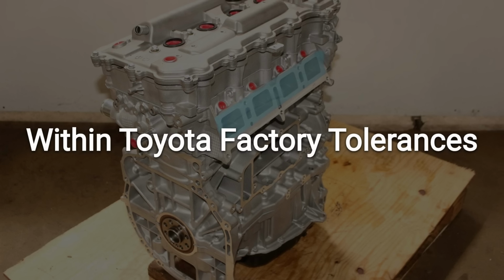The timing chain guides, which are plastic composite pieces that the chain rides against to control chain slap and vibration, showed slightly more surface wear on Car A as well. Neither engine was anywhere close to a failure point. Toyota's timing chains on this engine are rated to outlast the engine itself in most cases. But if you're looking for where full synthetic oil earned its keep, the timing chain assembly is a legitimate answer, because that thinner, more thermally stable synthetic film handles the high-load, high-friction contact between chain and sprocket a little better over time.